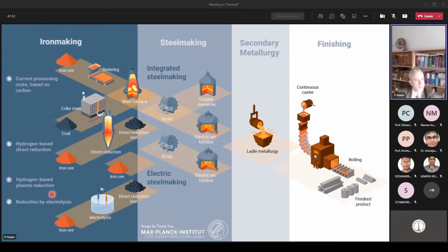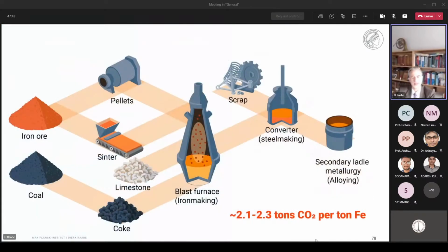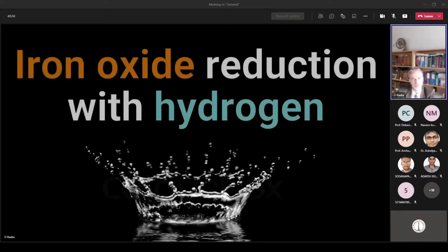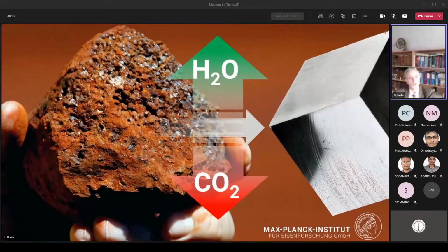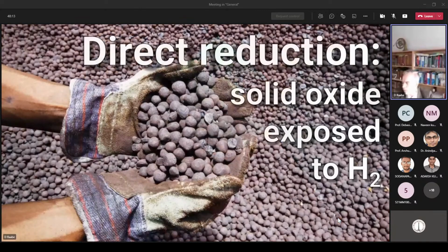Now, the direct reduction based on these classical Midrex shaft furnaces, but also fluidized bed reactors, are interesting alternatives because they can be operated with hydrogen. And of course, electrolysis, but electrolysis is not our topic today. So this classical blast furnace that we all know very well carries about 2 to 2.3 tons of CO2 per ton of steel. And again, there are different calculations pertaining to different companies, different plants, and so on. But give and take, we talk this amount of CO2 per ton of steel. And an alternative is obviously to use hydrogen as a reductant, because then you are producing water instead of CO2.